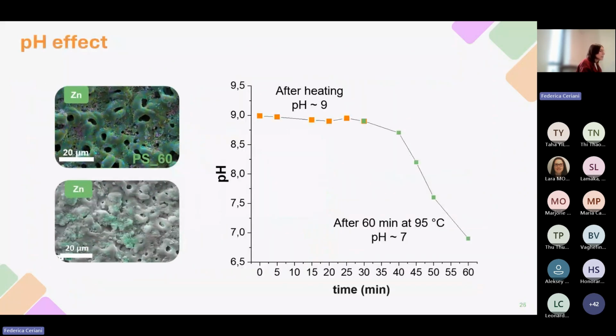So we measure the pH of the sealing bath during the entire duration of the sealing post-treatment, and it is observed that the pH value continuously decreases, and in particular, after 30 minutes of treatment, it drops, reaching a final value at the end of the 1 hour post-treatment close to 7. As I said before, such low pH could cause a partial dissolution of the already existent precipitates, leading to an almost complete disappearance of the lamellas that already exist on the surface, and then to a loss of the sealing effect.